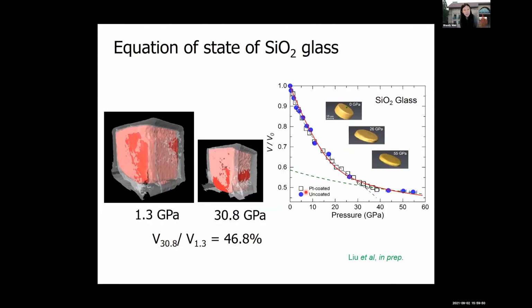Okay, so emboldened by the success, we began looking at more Earth-relevant compositions like SiO2 and silicate glasses. But these are made up of elements that don't have a lot of electrons, so it's more challenging to get good absorption contrast at the energies we're looking at. So in early experiments, we tried coating our SiO2 cubes with a thin layer of platinum. So this cube was initially 15 by 15 by 15 microns, and then we coated it with some platinum. It's hard to get even coating, so that's why you see some of the SiO2 poking out here.